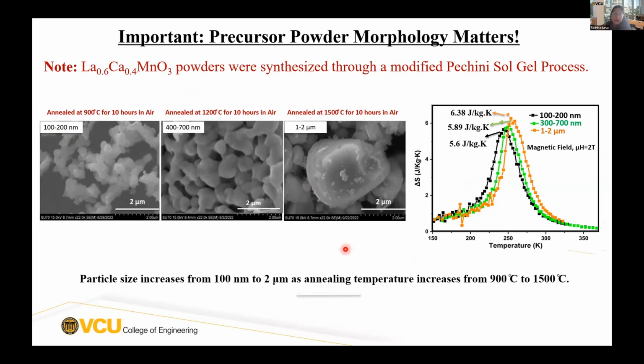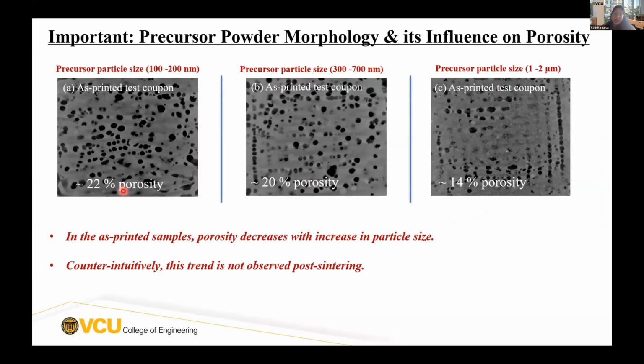So we made batches of samples with different particle sizes and 3D printed them. Here is a tomography of the particles, and you can see that larger particles show less porosity, while smaller particles show around 20% porosity. So in the as-printed samples, porosity decreases with increase in particle size.